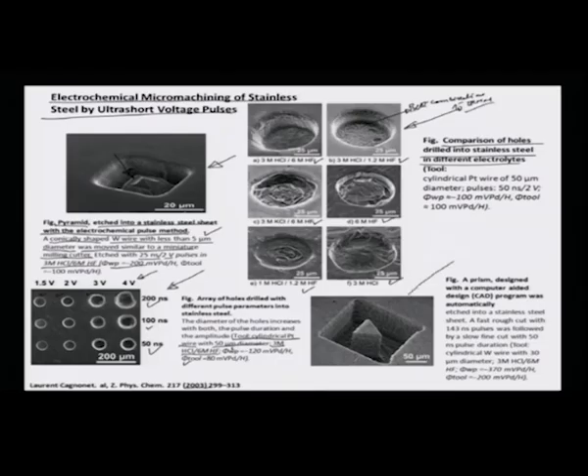Here again is a very beautiful SEM picture of a prism, and this has been designed with a computer aided program, and it was etched in stainless steel. This was actually done with a fast rough cut of 143 nanosecond pulse duration using ECMM, and then a slow fine cut of 50 nanosecond pulse duration was used in this particular case. The tool in this was again a cylindrical tungsten wire with 30 micrometer diameter.